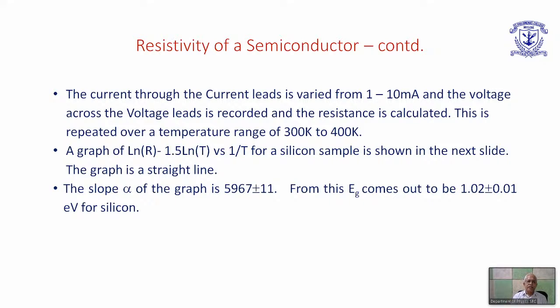So in the experiment, the current through the current probes is varied in the range 1 to 10 milliamperes. The voltage across the voltage leads is measured and recorded. The experiment is done over a range of temperature from room temperature to about 100 degrees centigrade, or something like 300 to 400 degree Kelvin. As I said before, from the data, we evaluate values of ln R minus 1.5 ln T, and then plot this along the y-axis versus 1 by T on the x-axis. And then we see that the graph is a straight line.